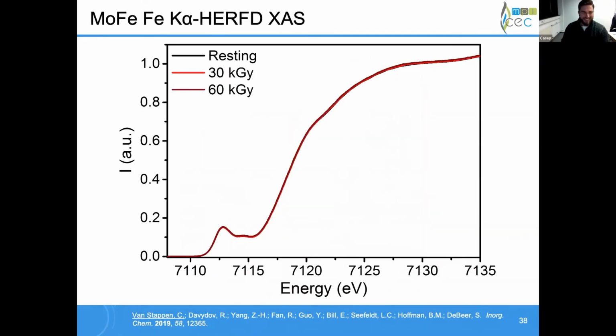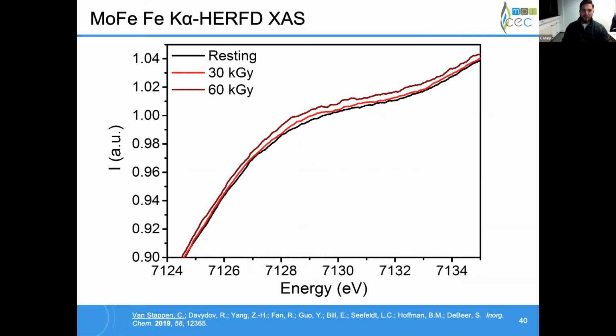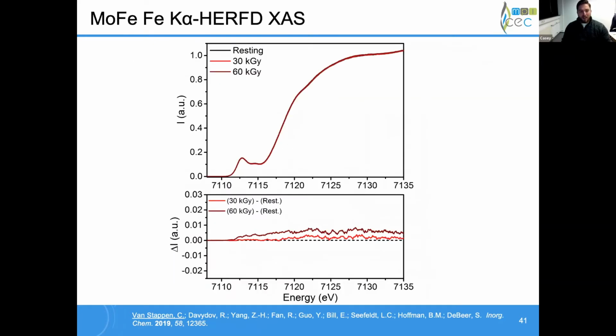Now, if we look at MoFe protein, big moment. Oh, there's almost nothing. Like, what's going on? So it doesn't look like anything's changing at molybdenum, and it doesn't really look like anything's changing at iron, except if we look really, really close, there's a small change in the white line that we can observe, but this is tiny. It's kind of laughable, right? If we look at this different spectrum, we see a general increase in intensity across most of the edge, but this is, you know, 0.5%, like 0.7% or so.